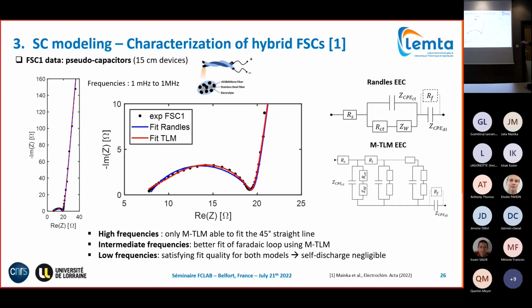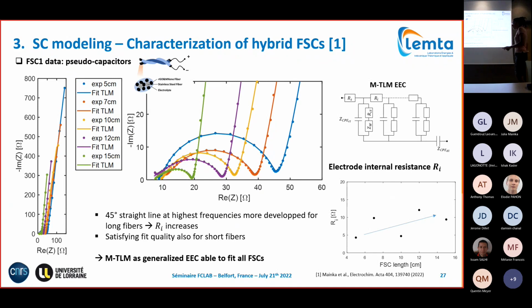And at the lowest frequency, we have a satisfying and identical fitting quality for both circuits, which is logical because electrical double layer charge storage is modeled in the same way for both circuits. Just note here that we have satisfying fit quality without the need of connecting a self-discharge resistance, which means that self-discharge seems to be negligible for these devices, at least in the analyzed frequency domain. Okay, so we validated our model for our devices.